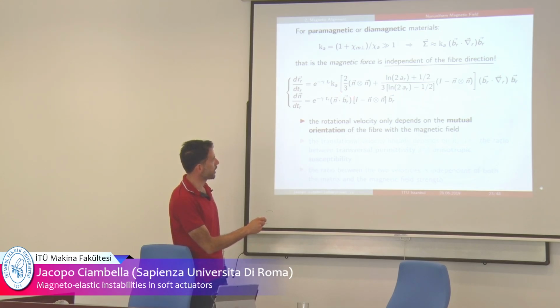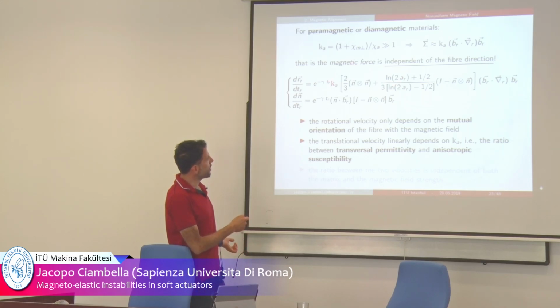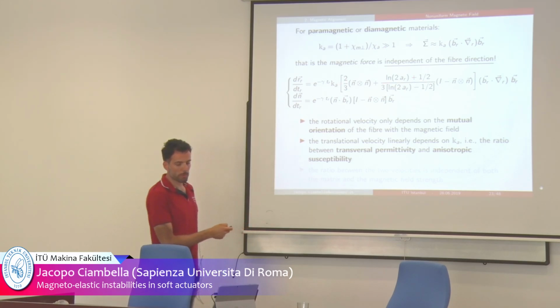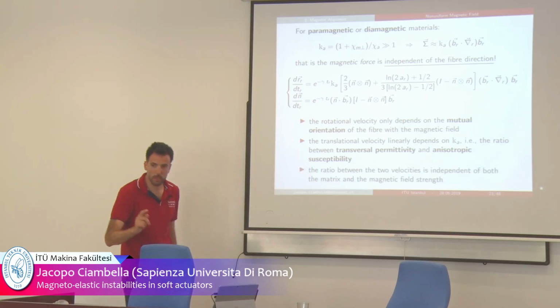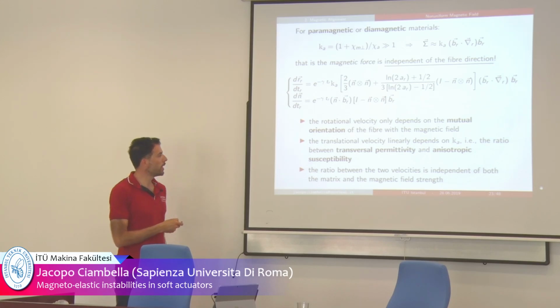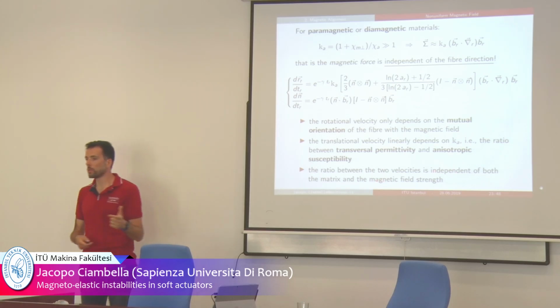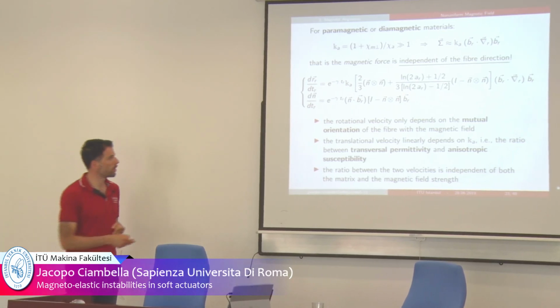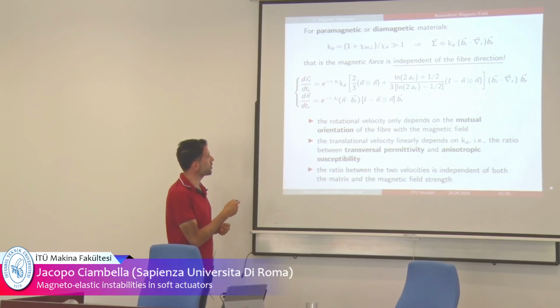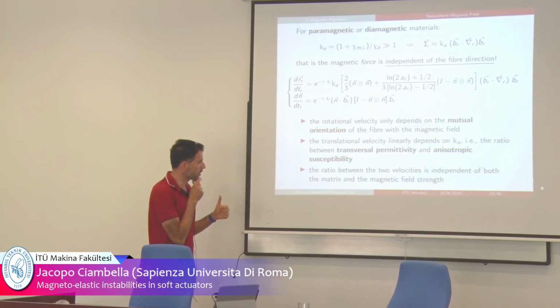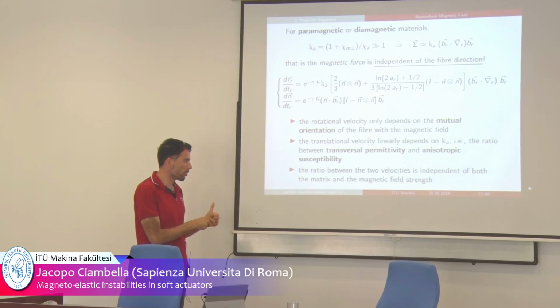So the rotational velocity only depends, as before, on the mutual orientation between n and B_R. The translational velocity depends on what? It depends on this parameter Ka, which I said is much larger than 1, and of course on the aspect ratio of the particle. But what is interesting is that the ratio between these two velocities is independent of the matrix properties and the magnetic field intensity. It only depends on the geometric properties of the particle, right? So the ratio between translational velocity and orientational velocity only depends on the geometric properties of the particle and not on the matrix properties, so curing time, viscosity, or the magnetic field strength.